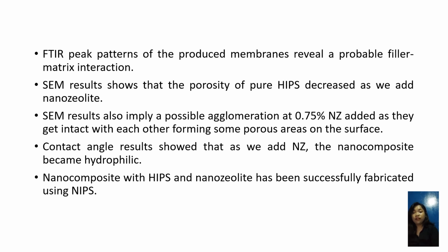The results of the characterization of the nanocomposite show that the hydrophilic property improves as nanozeolite is added. However, different ways of dispersing the nanoparticles are needed, as this may even allow smaller amounts of nanozeolite to cause a controlled effect on the porosity while still exhibiting a hydrophilic character.